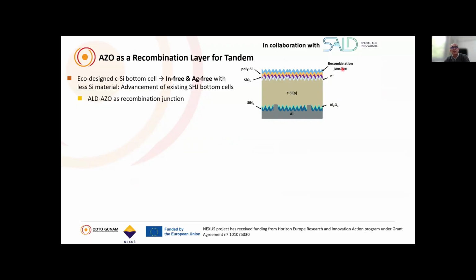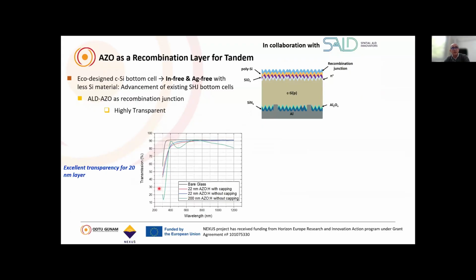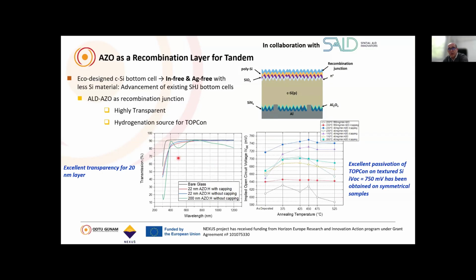So as a recombination junction on top, we are proposing to use aluminum doped zinc oxide. The transparency of the AZO layer is very good. This is showing the transmission measurement, but more interestingly, the implied open circuit voltage values are extremely high, very good values we have obtained, and up to 750 millivolt has been reached. So it is showing the promising future of this structure for tandem applications.